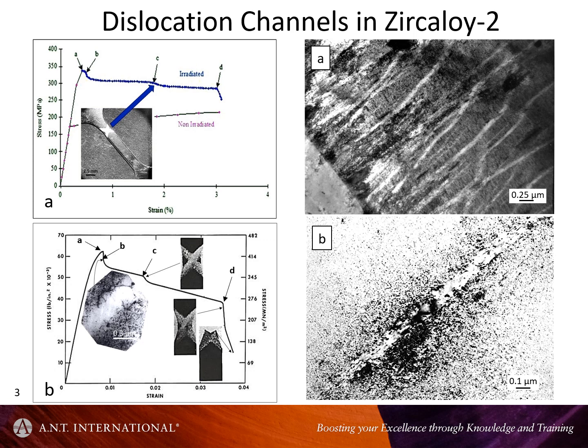If I was to summarize, channeling happens in irradiated materials, and it happens because, for whatever reason, the deformation, dislocation slip, becomes localized, occurs at a given point, and the dislocations run through the material, sweeping through the material in layers which are basically parallel with the slip plane, and sweep out the dislocations. In doing so, they create these dislocation loop free zones. And as you can well imagine, if you've got some radiation damage here and none here, this is a softer zone compared to the matrix.